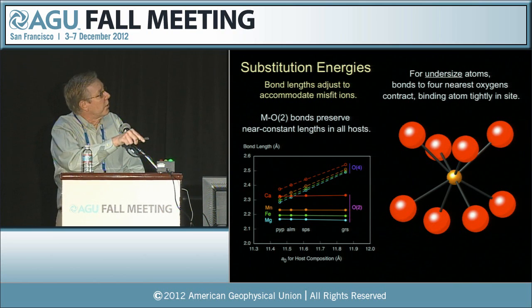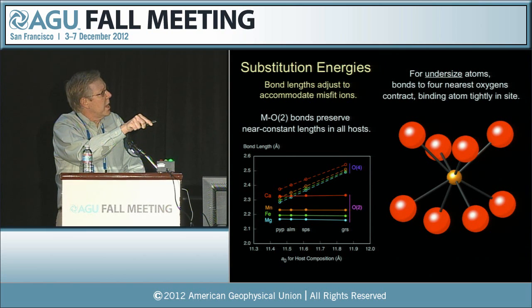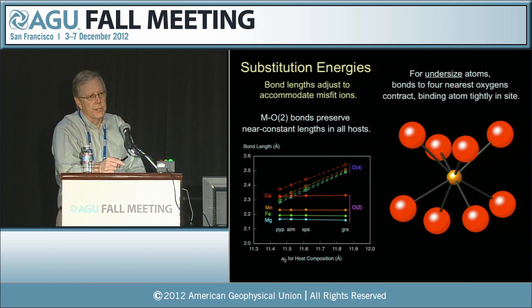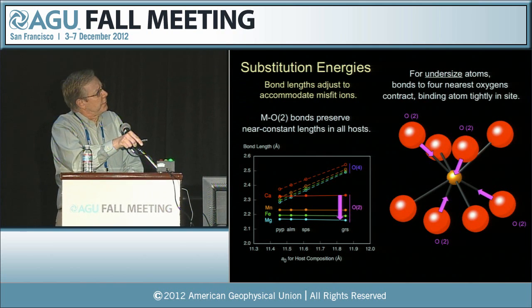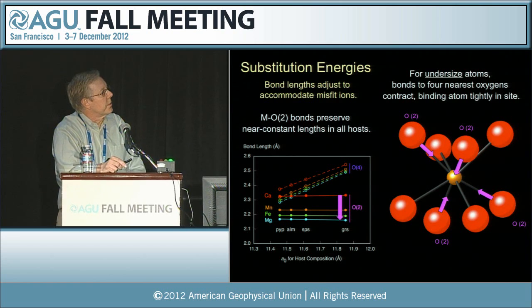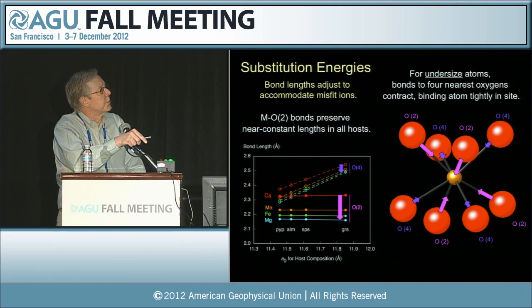And what's remarkable is that these MO2 bonds preserve near constant lengths across all of these hosts. So that means that if, for example, we have this as grossular and we substitute in a magnesium atom, these 4 nearer oxygens snuggle in around it, decreasing their bond lengths as shown here. And the same thing happens to a lesser degree for the outer atoms. So what we're doing is binding this smaller atom, this undersized atom, tightly into that site.